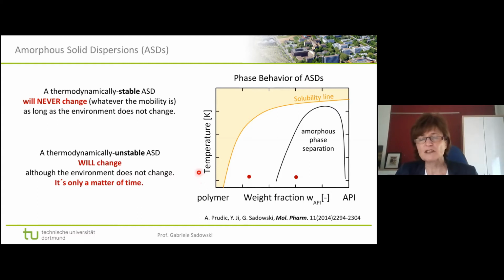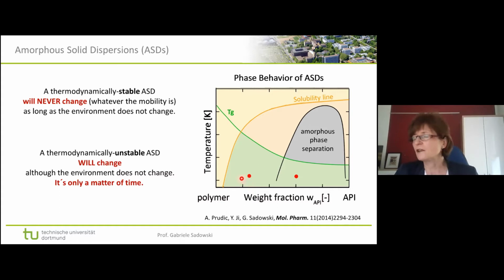What helps a bit, and this is good news, is that it's not only these two lines, but there is a third line which helps us, and this is the glass transition temperature. So we are in a polymer system, and polymers usually have a high glass transition temperature compared to the APIs. And that means all points below the Tg line, the green area here, have a very, very high viscosity. And this means that the mobility of the molecules is very, very low. So they want to crystallize because they know that they are right off the solubility line, but it will take very long. And of course, the bigger the distance to Tg, the higher is the viscosity. So the longer you can at least kinetically stabilize thermodynamically supersaturated ASDs.